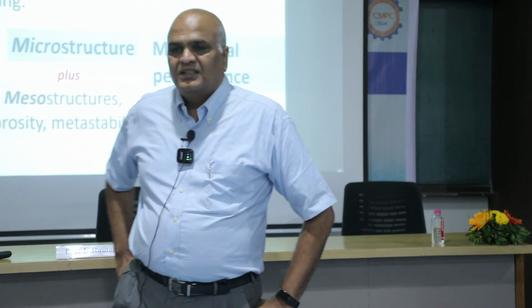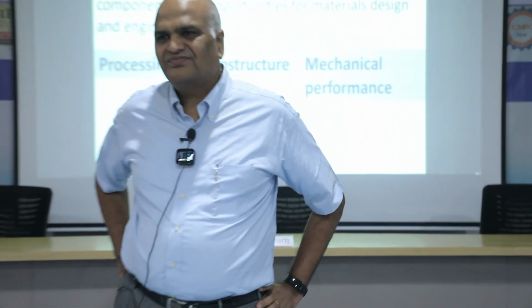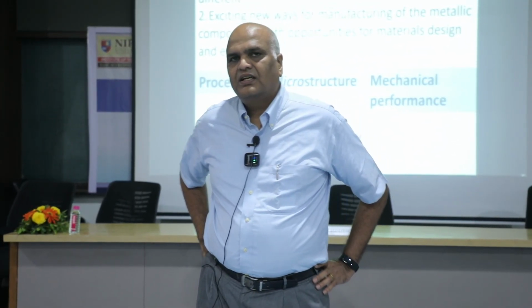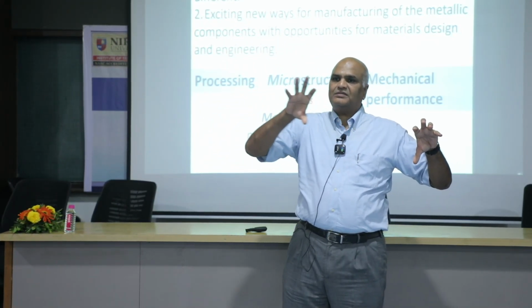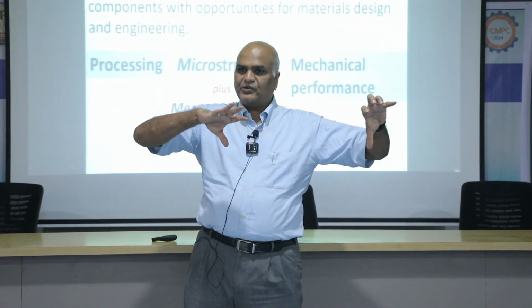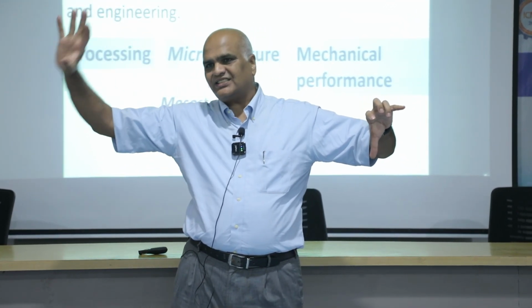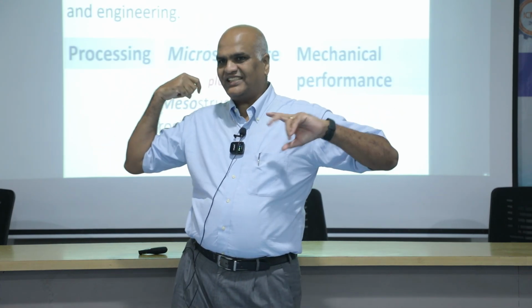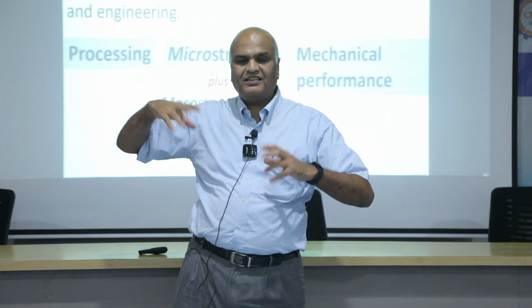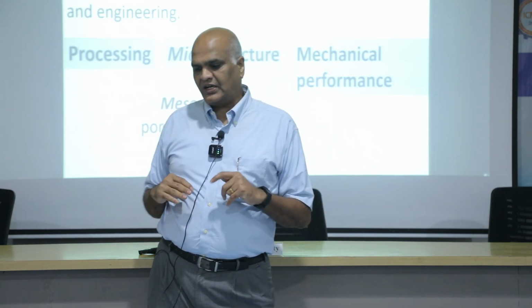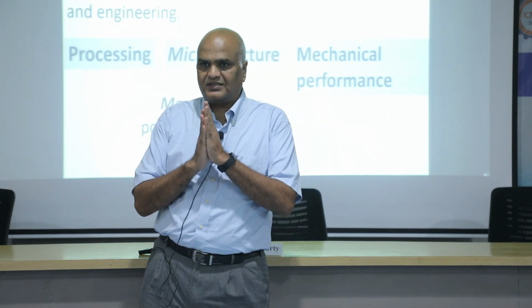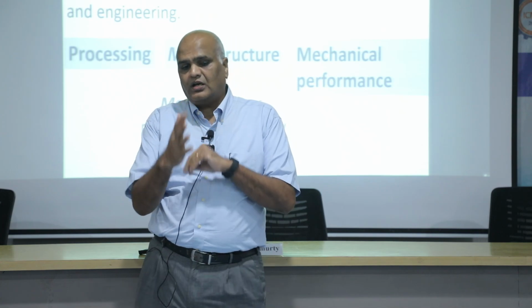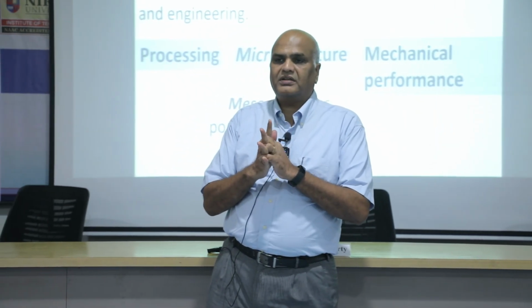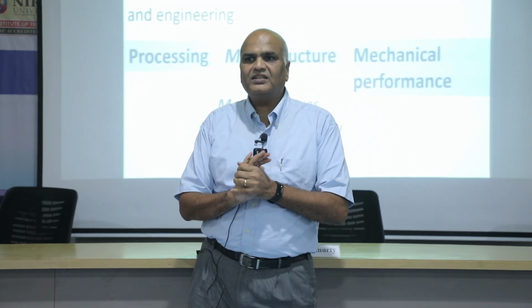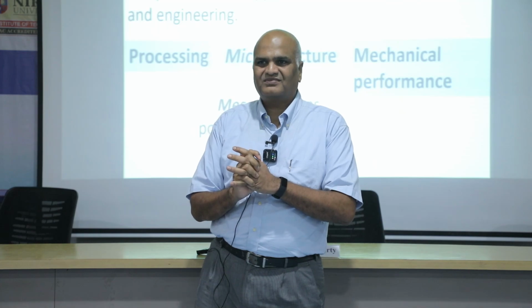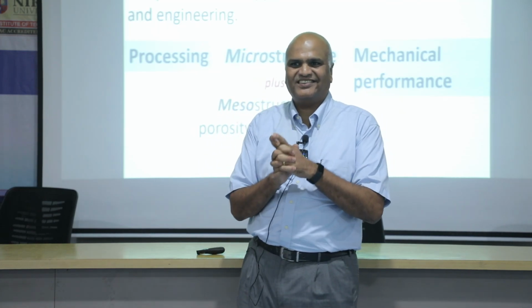How does the size of the metal powder affect the mechanical performance of the additive manufactured product? There is an intermediate step. The size of the powder affects the microstructure, and then the microstructure affects the part. I quickly showed coarse powder and fine powder, and I get very different microstructures there. There is columnar grain growth in most of these. If you have coarser powder, you could get more equiaxed structures. So there is a powder size effect very definitely. In fact, we have a Nature Communications paper on this very aspect on 316L.